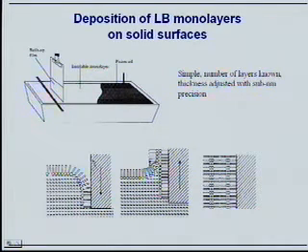And then this is a solid plate. You dip it down, you take a layer of surfactant with you on the way down. Then you pull it out, and you take another layer of surfactant with you on the way out. If you don't want the second layer, you can keep it on the water, move it, and take it out from outside the surfactant area. Then you can dip the same plate again, and this repeats itself.